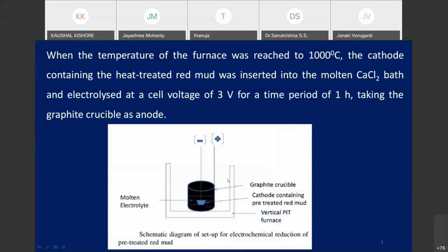So what will happen during electrolysis? The basket contains the red mud, containing various metal oxides. The oxygen will be removed to the electrolyte, and after passing through the electrolyte, it goes to the graphite crucible and comes out as CO2 or CO. So what is the cell voltage? The cell voltage is 3 volt, and we have kept the time period at 1 hour, and here we have electrolyzed the material at 1000 degree centigrade.